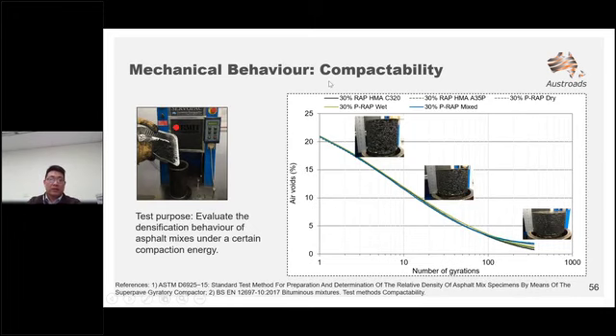So the first investigation, we look into the compactability of asphalt mixes. This test aims to evaluate the densification behavior of asphalt mixes under certain compaction energy. During the compaction, the sample height is reduced because it gets denser. As we can see, the incorporation of 30% RAP and PRAP did not show much difference before 100 gyrations. But after 100 gyrations, there was a deviation in the densification behavior, and it was mainly affected by the source of RAP and PRAP used in the mix. However, overall, the inclusion of 30% of PRAP didn't show an adverse effect on the compactability of asphalt mixes compared to the RAP.